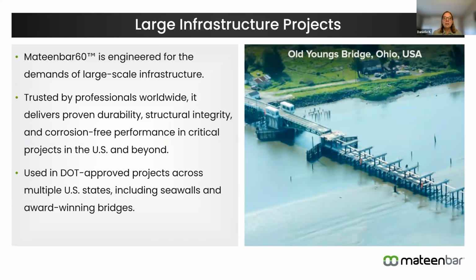So really what we want to talk about today is the reason why GFRP is applicable. We're really touting it for these large infrastructure projects. In particular, the decks, obviously, that are exposed to either, in this particular case, a marine environment and or de-icing salts. Obviously, many states across the country use a large amount of de-icing salts. And so this is really where, in these large infrastructure projects, we're seeing, one, the effects of corrosion, but then two, the advantage of possibly using GFRP as an alternate.